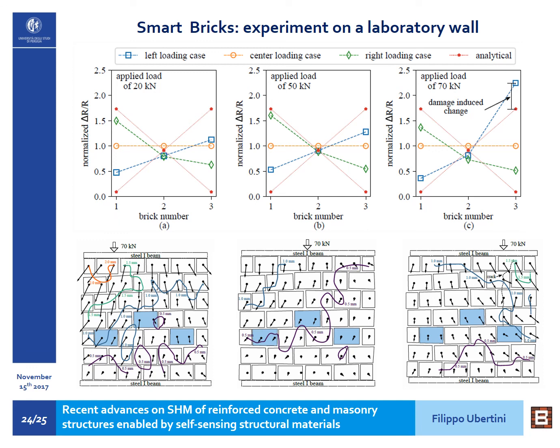But when the load reaches the value of 70 kilonewtons, we have clearly a deviation in correspondence of brick number 3 for the left loading case from the previous reading, and also a large deviation from the analytical prediction. This is due to the fact that at this loading condition, the wall has started to fail in compression in the region under the load, and a vertical crack has formed in the masonry. So the formation of the crack has resulted in a clear change in the response of the bricks, and we can therefore conclude that the bricks are suitable for being used for strain sensing as well as damage detection in a masonry structure like the one shown.